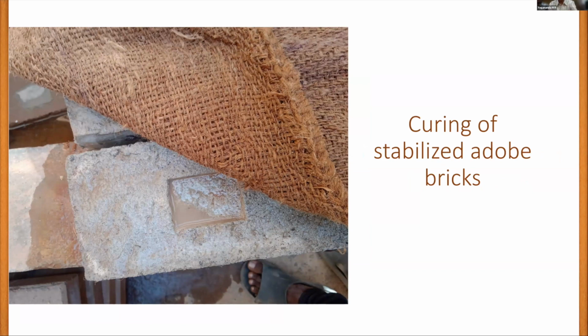This is the method of curing. We put normally wet burlap and cure it. You don't need much water. Make sure that the bricks do not dry. That's all. So you just sprinkle water, cover it with hay or gunny bag, keep it wet.